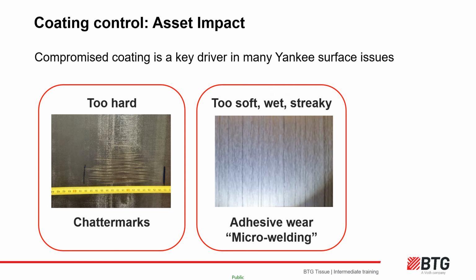On the other hand, if coating is too soft, wet or streaky, then you should see sheet control issues as an early sign. Floaty sheet may be felt following, perhaps even blistering if the Yankee is also too hot. This could be a result of too much release and not enough base coat, a chemical wash perhaps, or simply a high sheet moisture, either fully CD or just a peak washing the coating away. Even a combination of these.